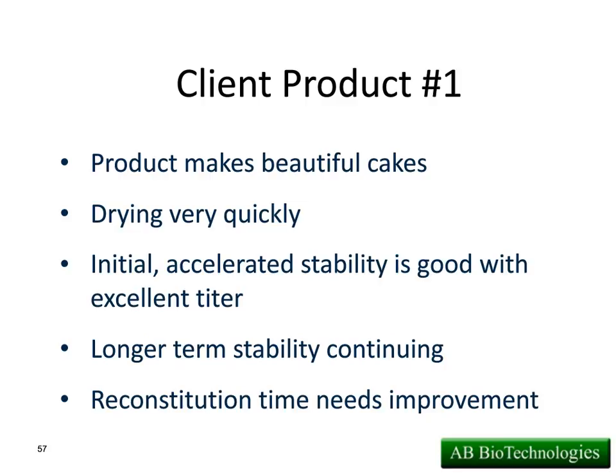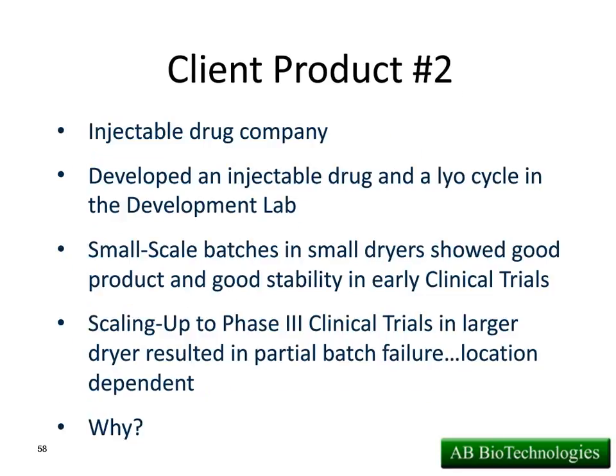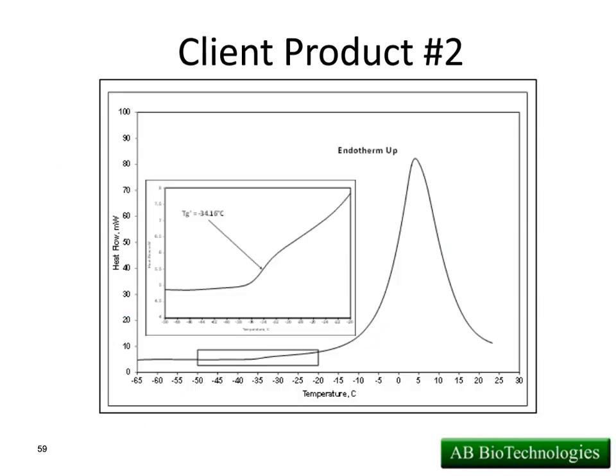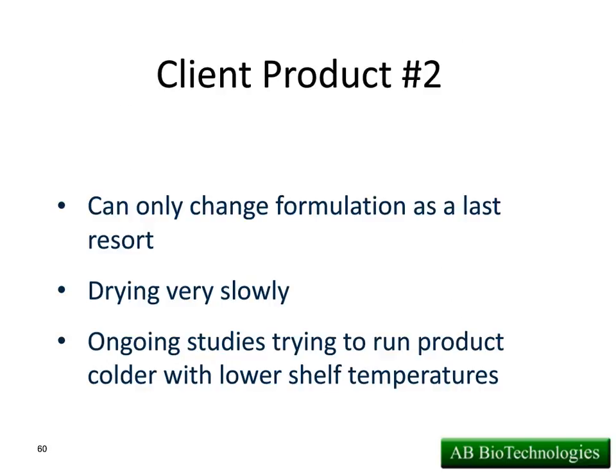Okay, for the next product. This was an injectable drug company. The small-scale batches showed good freeze-drying, again, when they were doing this in the development dryer. However, when they scale it up, everything fails, starts to collapse. Now, why is this happening? Well, we went through, and the first thing we do, again, the DSC comes into our lab. In this particular case, it was running right around negative 34. So what we ended up doing was this product was drying very slowly.